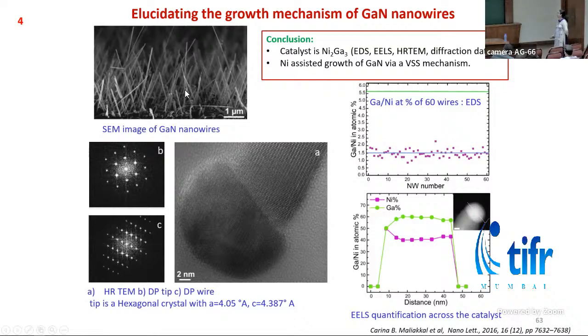And when we looked at the phase diagram of nickel gallium, we could find that Ni2Ga3 cannot be in liquid form; it is in solid form at the growth temperature of the wires. That means this growth has happened via the VSS mechanism, that is, the vapor solid solid mechanism.